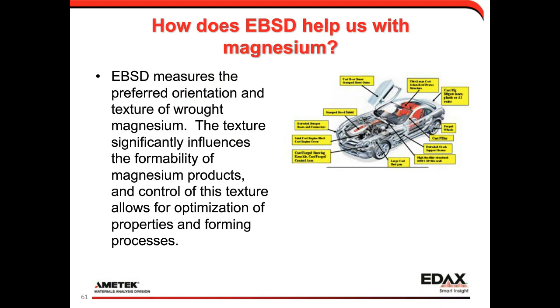Just as a quick note, EBSD can measure this preferred orientation, it can measure the texture. Texture strongly influences the formability of magnesium, and control of this texture allows you to improve your properties and forming processes. And that's just a little schematic showing where magnesium can be integrated into different components.